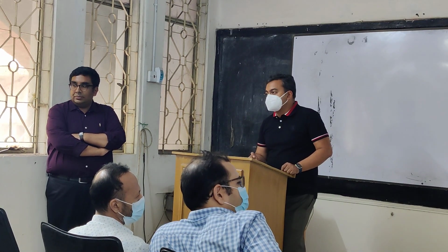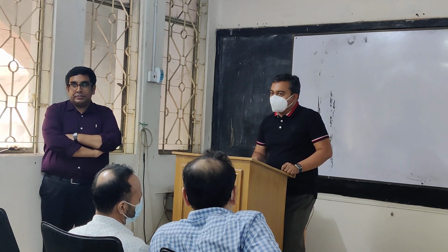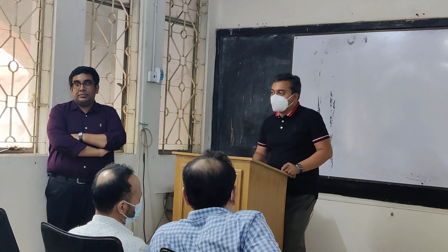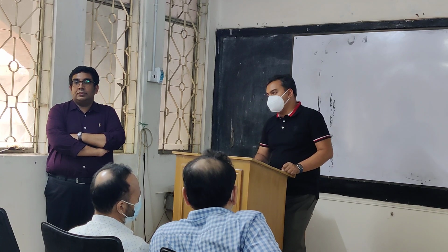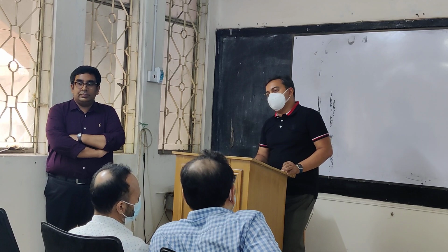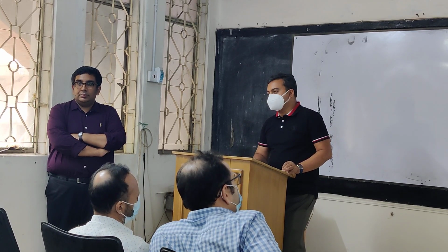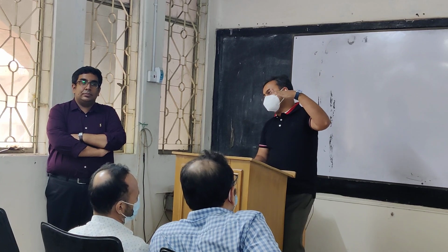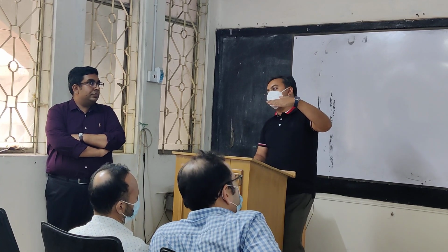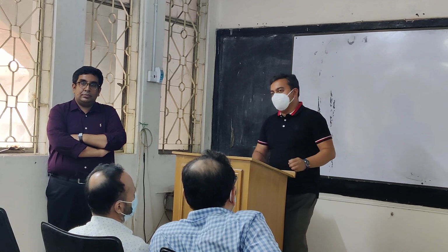So the growth technique is too fast, you have to control it. And the SiO2 part is done in a self-limiting process, so for SiO2 we don't have to worry. It goes through that 8 angstrom thickness and it stops.